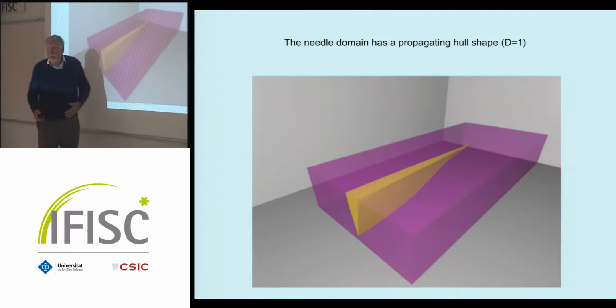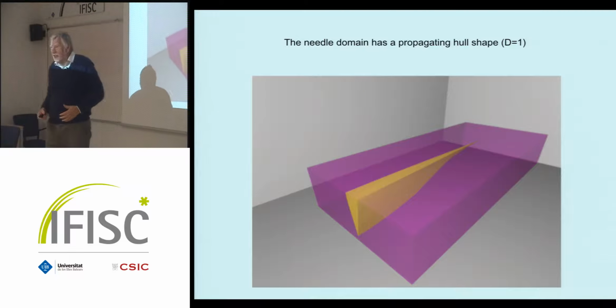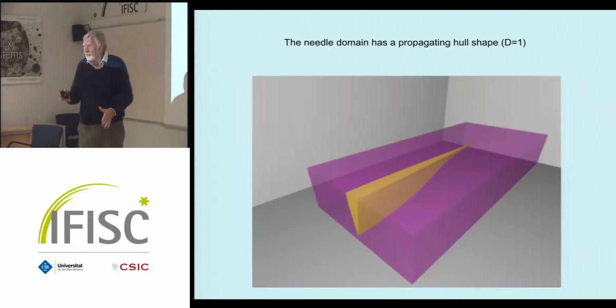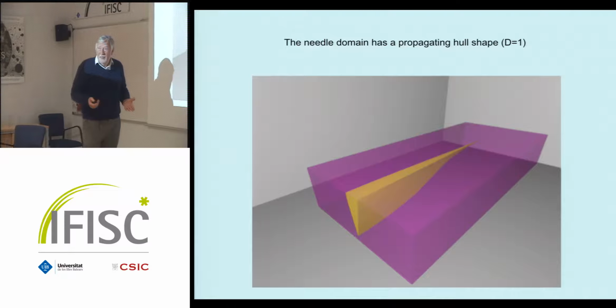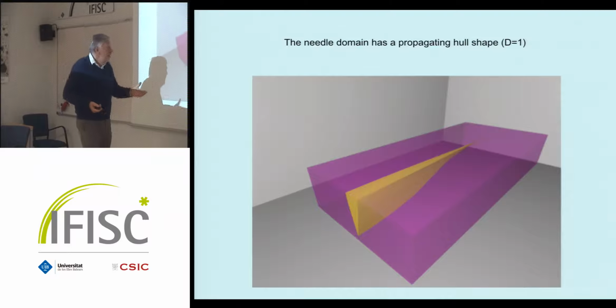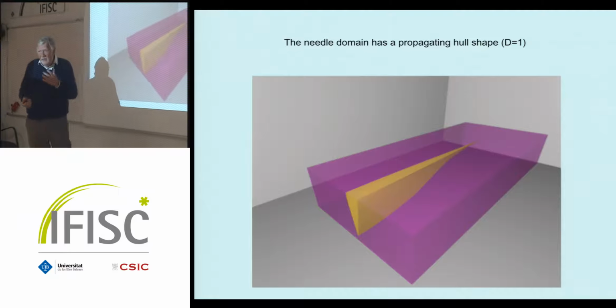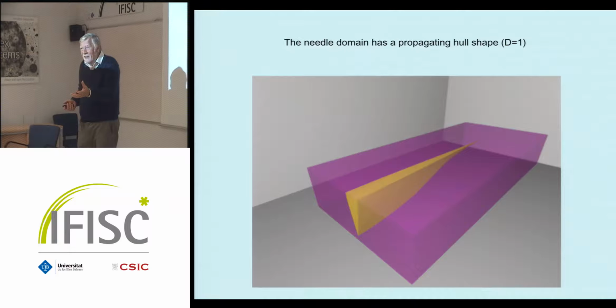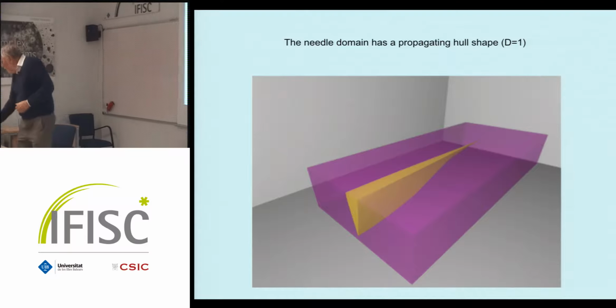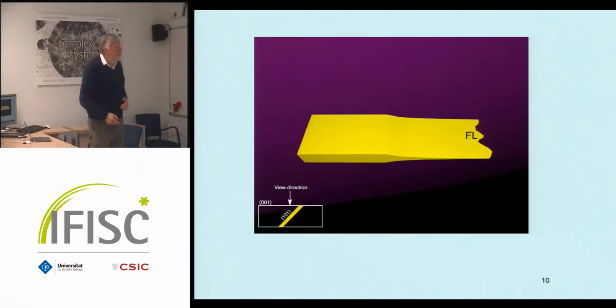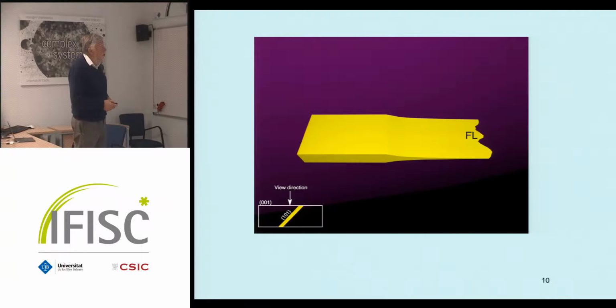Right? So you see they're actually themselves also quite complex, because in textbooks they're always parallel walls and everything is fine and so forth. But you are strained. I mean, your material is deformed. And so these ones have to follow the energy minimization, but of the deformed area. And if it's deformed, then you see that these lattice planes are actually no longer parallel and so forth. Now, if you look at that, this one's actually from a photograph. So here are straight walls, and then the needle tip comes in here, and FL means front line. That is the top thing which goes forwards and backwards.